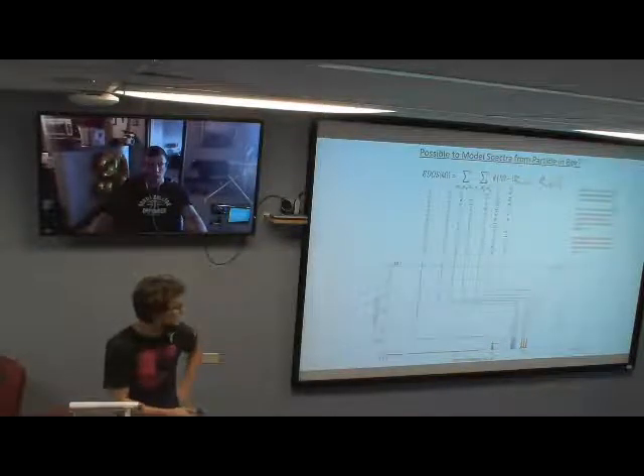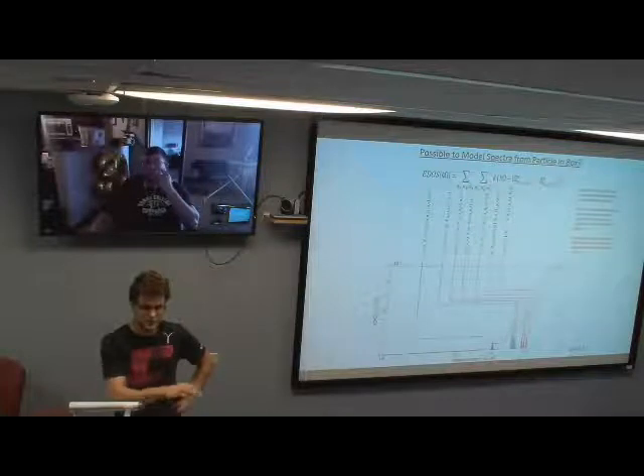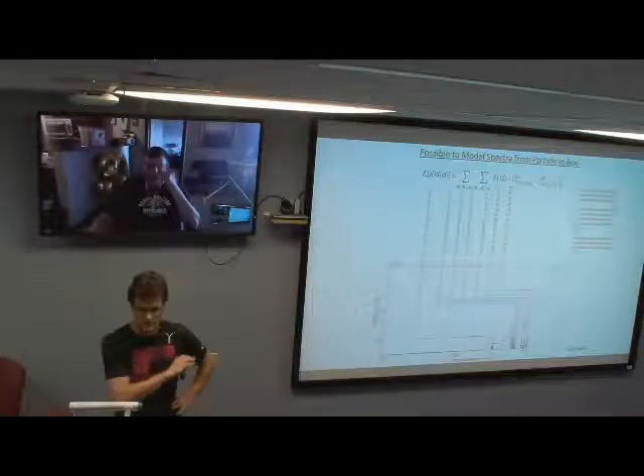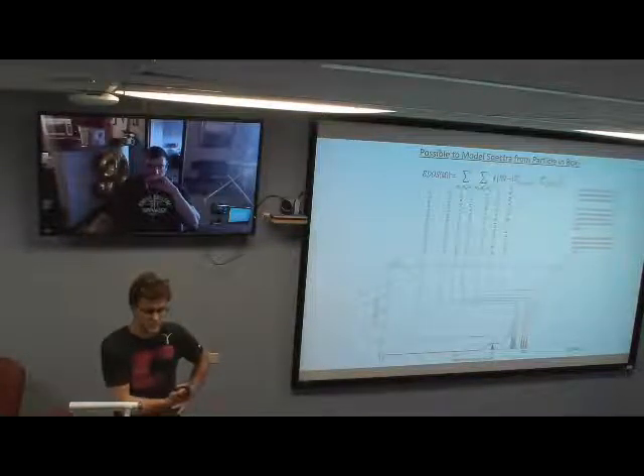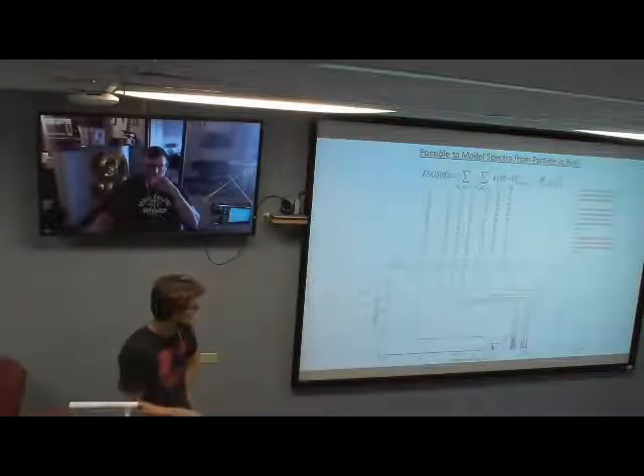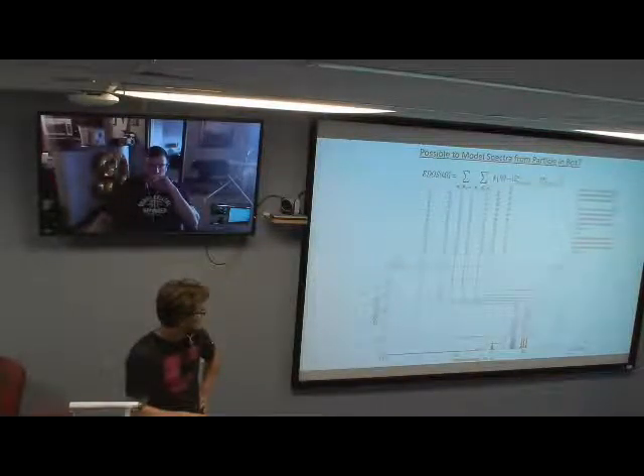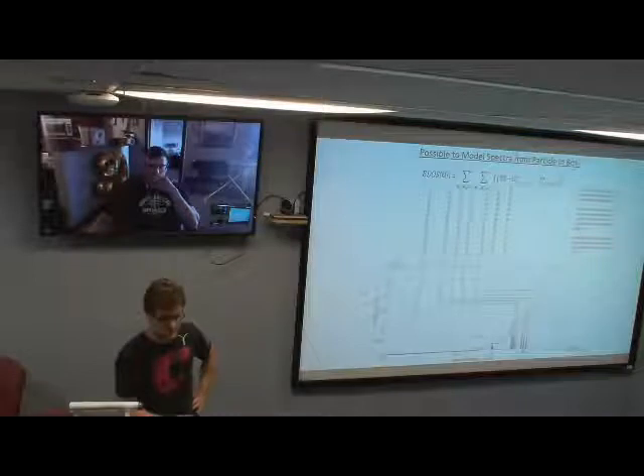So this energy here would be like the HOMO-LUMO transition. So here you're not really looking at the transition density values, right? Right, this is just looking at bright or dark, all possible excitons which you can make within a certain energy range. So here would be from 3 to 4 electron volts. But it's interesting that you already have this kind of shape structure and some features, even if you're not applying the selection rules, right? Which will probably make it even more structured.